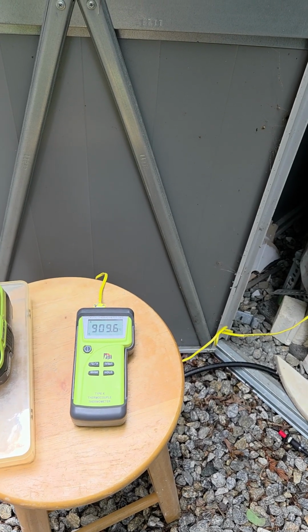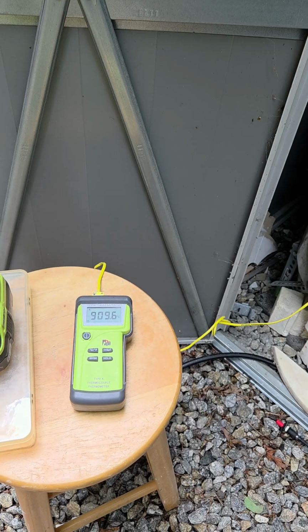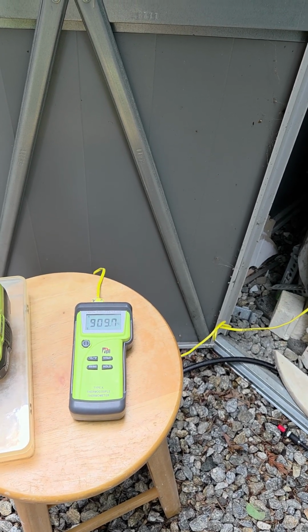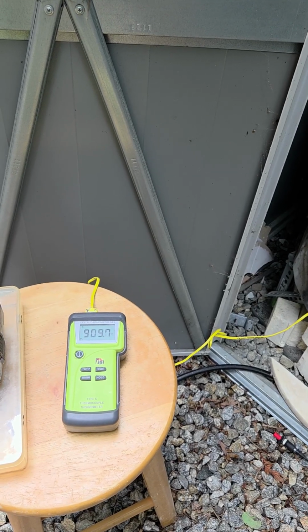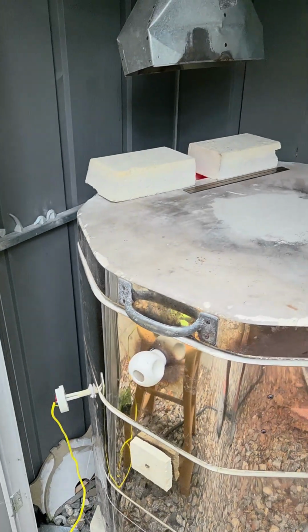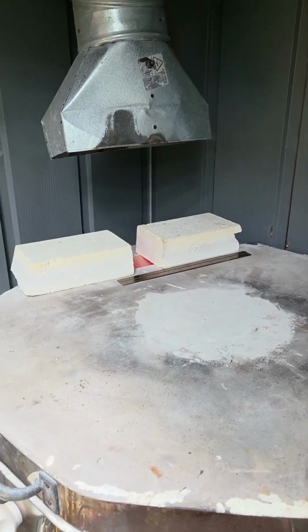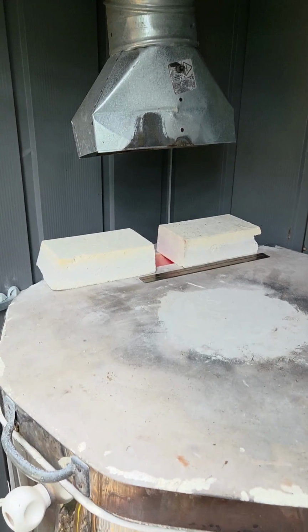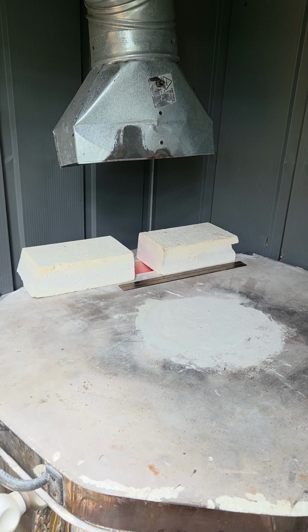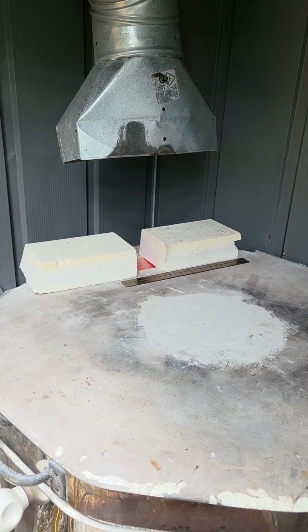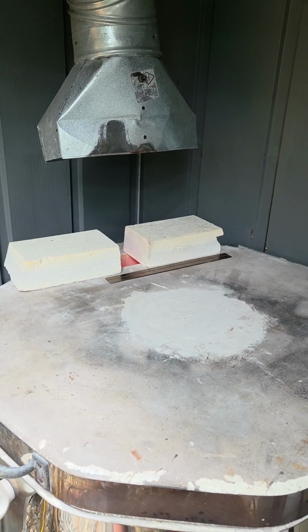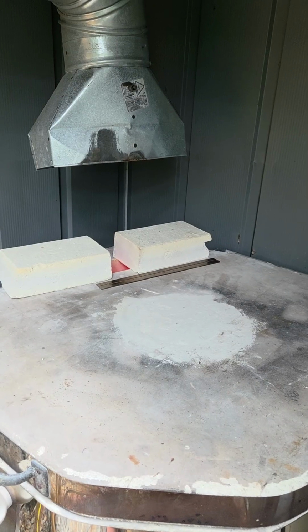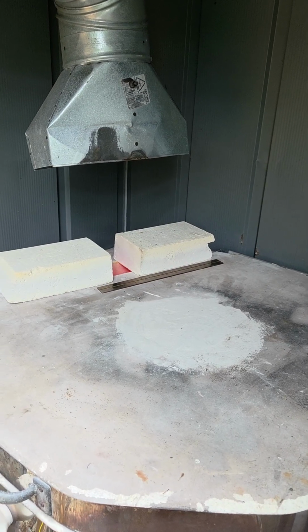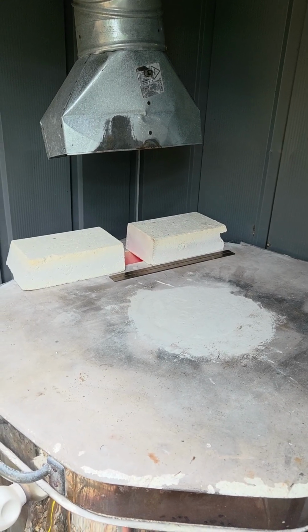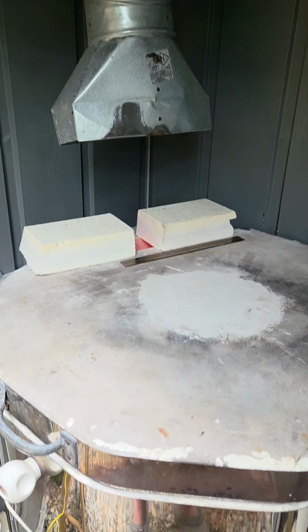One doesn't want to let it go over 950 degrees because the glaze is going to start melting and one won't get a good body reduction. And this setting requires a little bit of tweaking. Sometimes as little as a 1/16 of an inch movement of one of these blocks can cause the temperature to start rising. I'll let it go up to about 925 or maybe 930 at most, and then I'll push the block in a 1/16 and it might start descending, and I'll let it get back down to 910 degrees, and it sort of oscillates back and forth during that 40 minutes. After the 40 minutes, it gets opened up a little bit and we start the climb to the finish.